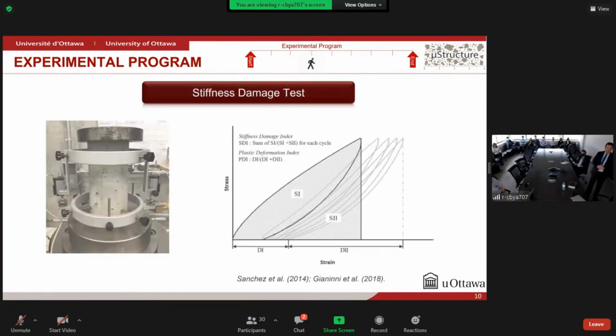So SDT is a great tool with which we can quantify the distress degree in concrete. And besides the modulus of elasticity as an outcome, it also gives the stiffness damage index, which is the ratio of the dissipated energy to the total energy applied to the system, but also it gives the plastic deformation index, which is the plastic deformation to the total deformation implemented into the system.